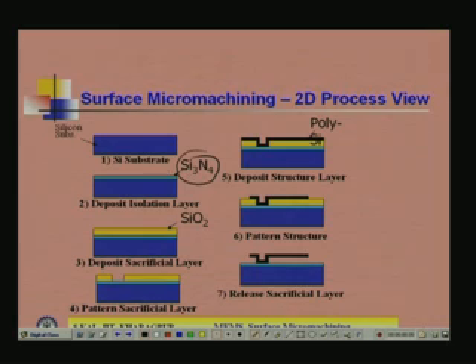After silicon nitride is deposited, that is basically known as the isolation layer, which isolates the substrate and the structure, that is why it is known as the isolation layer. Now, we come to the third diagram, which is the silicon dioxide deposition and then patterning, which is a sacrificial layer. The sacrificial layer is always removed later on. So, the silicon dioxide is deposited, then by using photolithography we pattern it, we make a hole in this particular location.